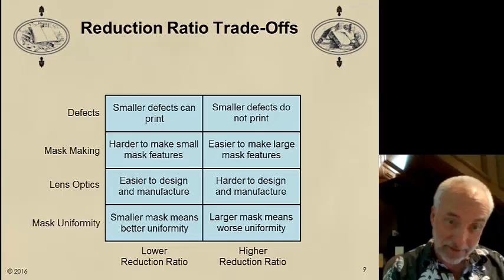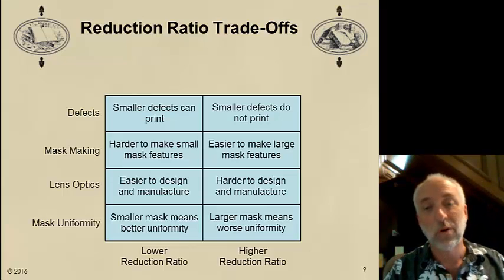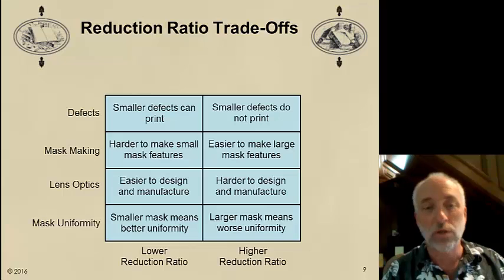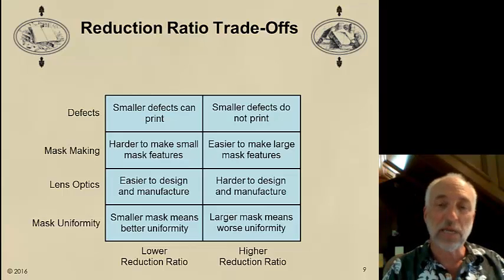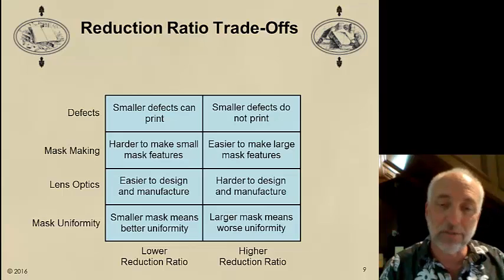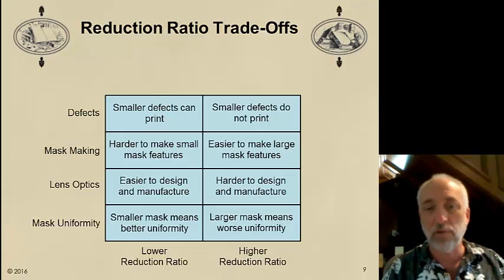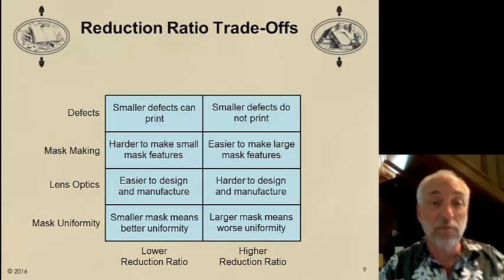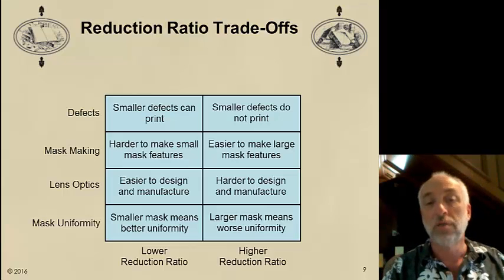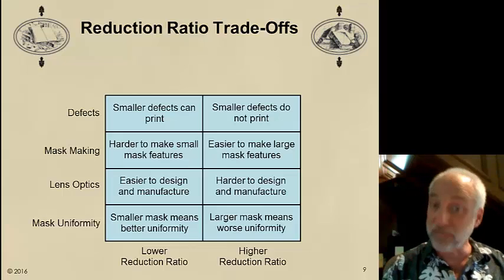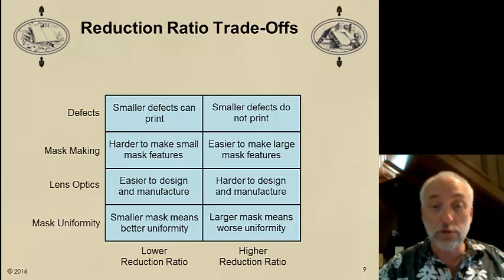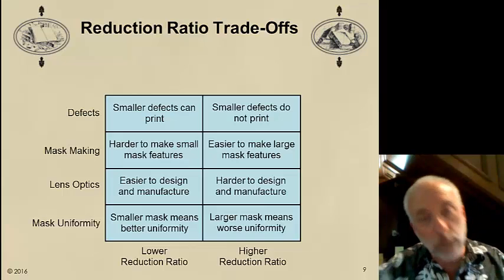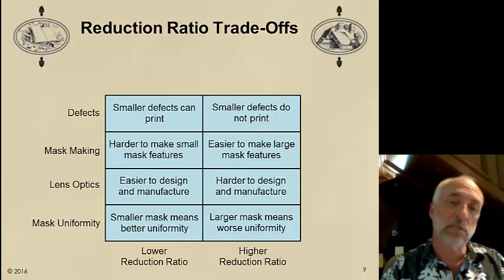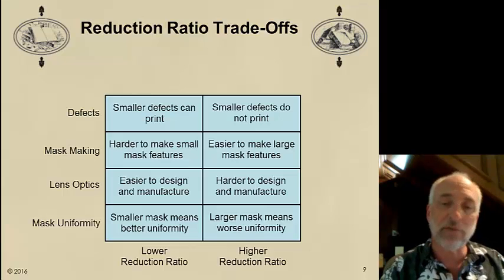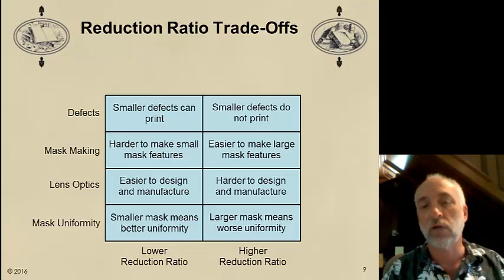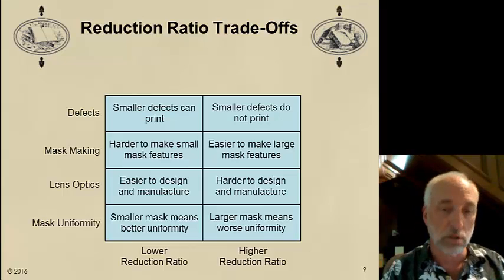Mask uniformity, on the other hand, also pushes us towards the desire to make smaller masks. If you think about it, if I have an 8x magnification instead of a 4x magnification, for example, then my mask is going to be twice as wide in both dimensions. Instead of, say, a 6-inch by 6-inch mask plate, I'd have to have a 12-inch by 12-inch mask plate. These larger physical masks make it harder to get uniformity across the mask. Right? Instead of uniformity across a 6-inch blank, you have to get uniformity across a 12-inch mask, and that's always harder.